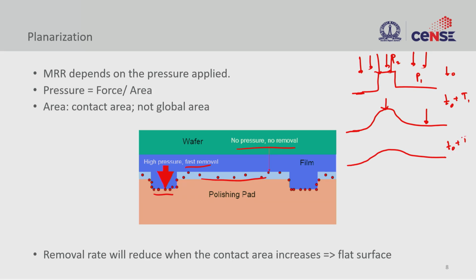This is T1 plus T2, and now because the topography is reducing here, you see the topography is reducing and your pressure that you apply is also reducing now. So now after a while this will become something like this, and then this is T0 plus T3, and this is where you achieve flatness, right. Beyond this point, what you do is you keep this profile uniform, right.